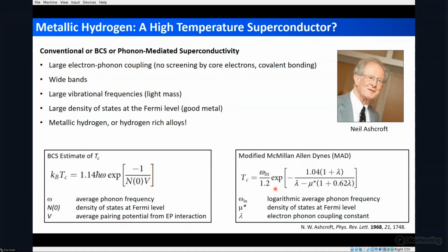And here I present a more modern version that can be used to estimate TC. This is known as the modified Macmillan-Allen-Dynes equation, and it works relatively well for systems where you don't have a very high electron phonon coupling. But again, some of the keys is you want this large logarithmic average frequency. So light element systems are going to have higher TCs, and this large electron phonon coupling constant, which would be present in hydrogen because of the covalent bonding and the lack of the screening.